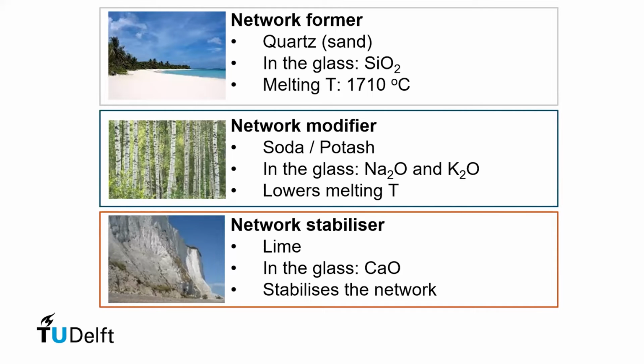So that's a problem. So in order to counteract that, they added a stabilizer, which is often lime, and results in the presence of calcium oxide in the glass, and this stabilizes the network.